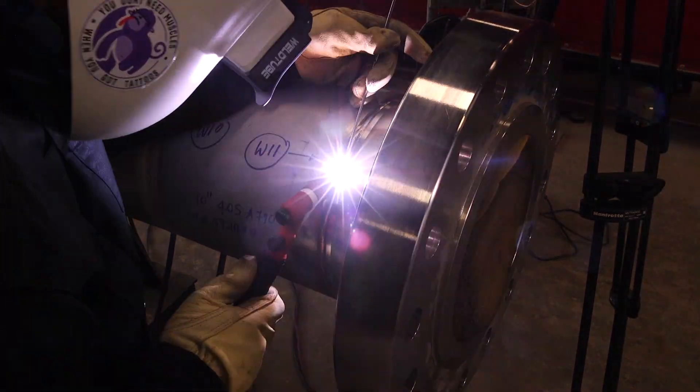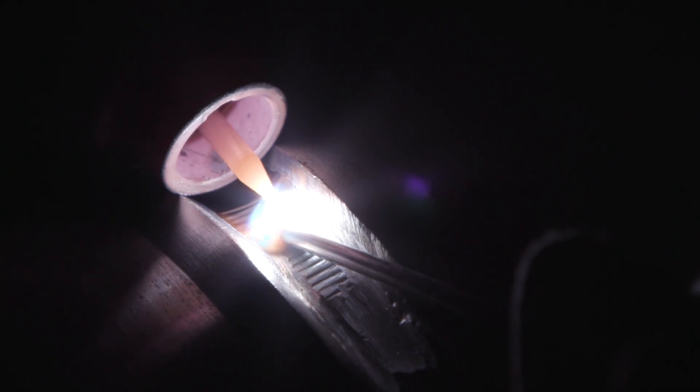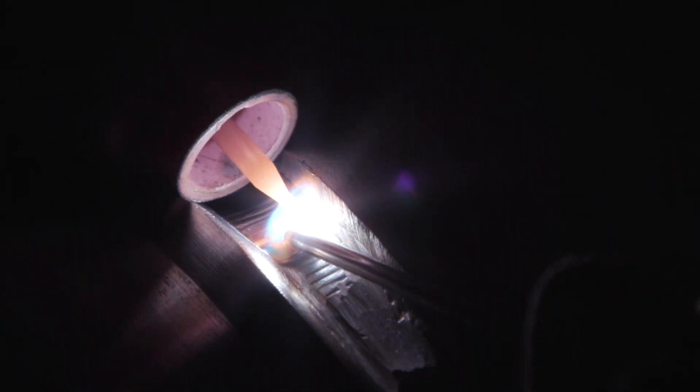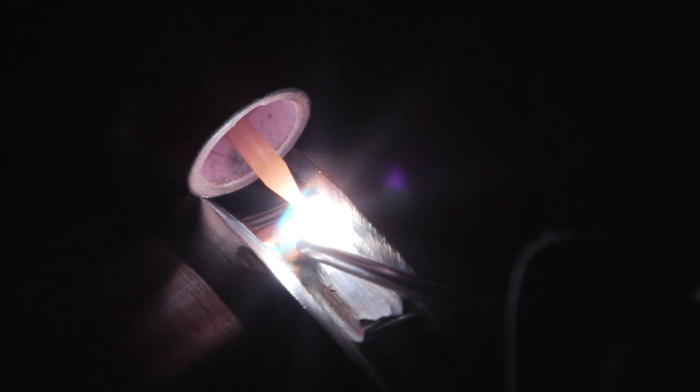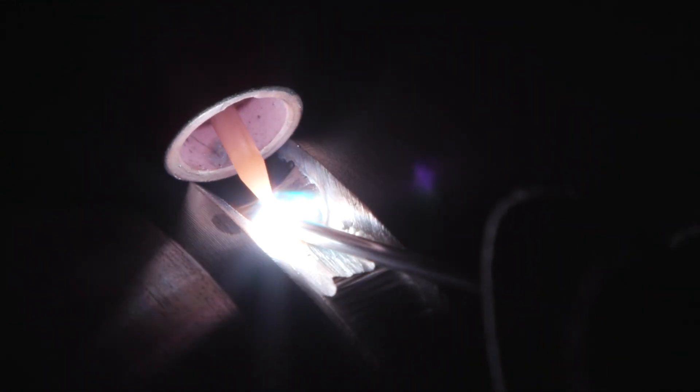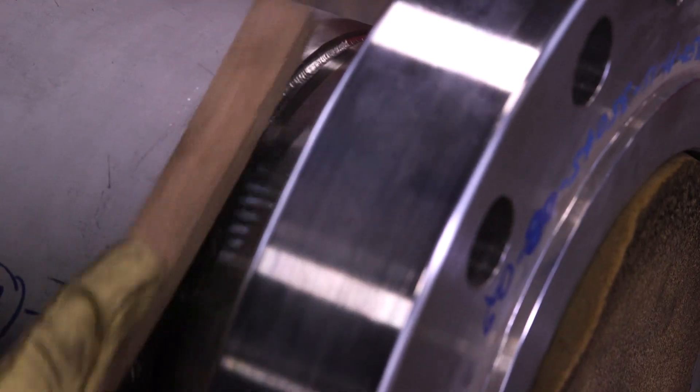And just another tip for purge lines, using bigger diameter pig tails if the person decide to go that way. Also, the person could use steel wool, stainless steel wool, on the end, which the argon would not shoot straight, the argon would simply hit the steel wool, and go every which way, you'd actually get a better quality purge using steel wool. The diffusers are not particularly fond of, I mean, diffusers, I'm not particularly fond of. The stainless steel wool I do like, especially if you're doing like titanium welding test or something, two-inch, you have stainless steel wool stuck down in there, the argon's come and have to blow through the stainless steel wool, and it just gives your high quality purge.